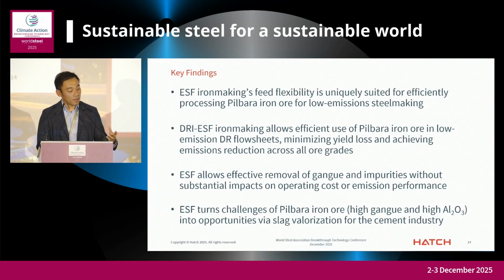And I think some of the other technical factors are not presented today, including the chemistry of that gangue. For example, I mentioned earlier, Pilbara iron ore has a slightly higher alumina content, but that's actually advantageous when using the ESF process because it produces a higher alumina ESF slag, which cement makers actually prefer, and you don't have as much need to dilute it down, compared to, let's say, a blast furnace having trouble getting above, say, 15% alumina in their slag. And of course, higher phosphorus: having a hot metal-based metallurgical process allows very effective phosphorus removal, whether it's hot metal pretreatment or BOF steelmaking. So again, it's a very well-suited process for all kinds of low-grade iron ore, but particularly a very effective solution for Pilbara iron ore in general.